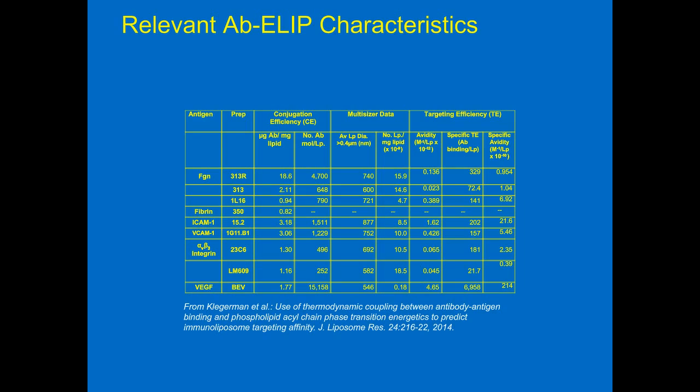This enables the liposomes to come through intact relatively quickly, but you have to calibrate it very carefully so that you exclude unconjugated antibodies. So these are some of the methods that we use. But there's a whole lot of other methods that are possible for people who don't have to worry about things like echogenicity, including centrifugal methods. So there are a number of ways to purify liposomes.